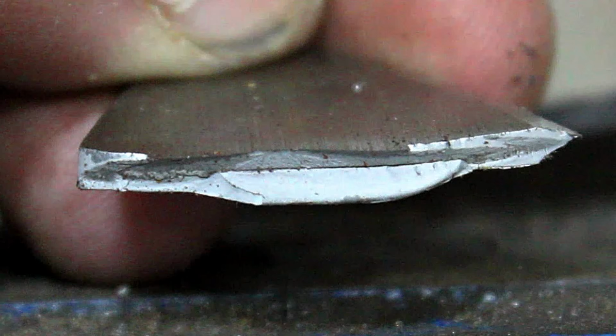If you look at the two halves, you can see these shelf-like features where the fracture isn't flat or uniform across the entire break. One section appears to have continued tearing while another section was still hanging on. That's a very uneven fracture, and to me that suggests this blade was absorbing a tremendous amount of force before it finally gave up. Now, can I tell you exactly why it looks like that? No, not yet. But it's one of the most interesting fracture patterns we've seen so far in this series, and it's definitely something worth investigating further.